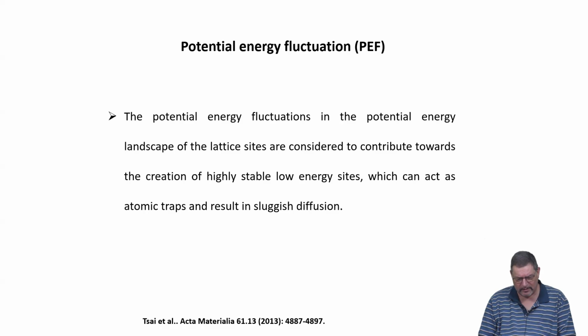Something we have not yet described or discussed is potential energy fluctuations. People discuss this for the high entropy systems, and it's related to these lattice distortions in a way, right? So you basically have more distortion, so you have a certain additional energy term because of these strains. So it's an elastic energy density which is added, and that gives you for certain sites an enhanced energy, and it will vary from lattice site to lattice site, and this is then called potential energy fluctuations.